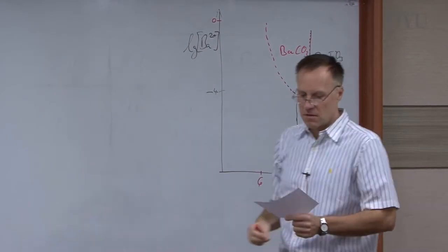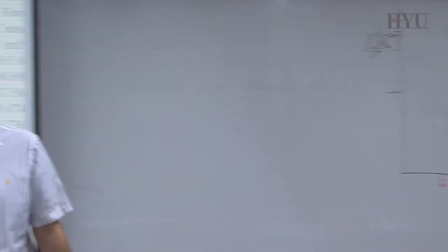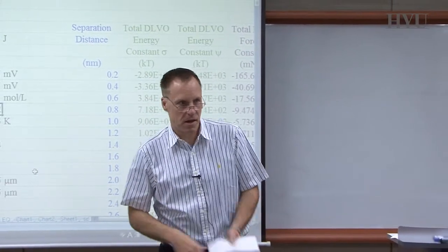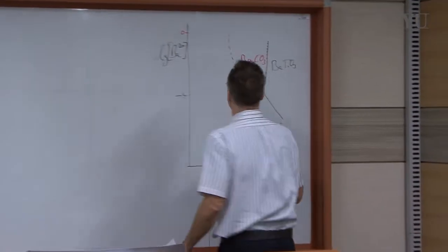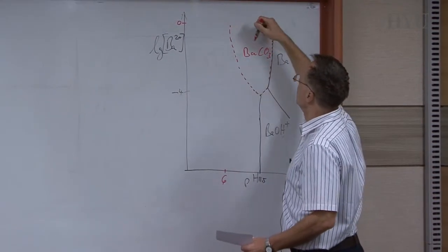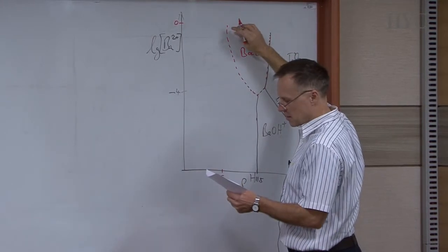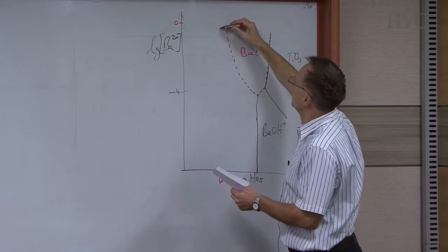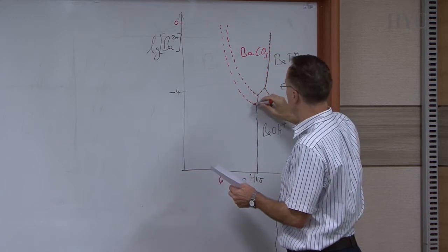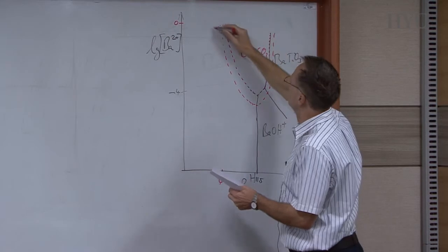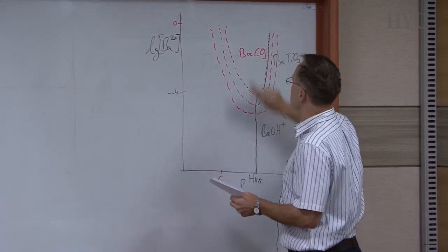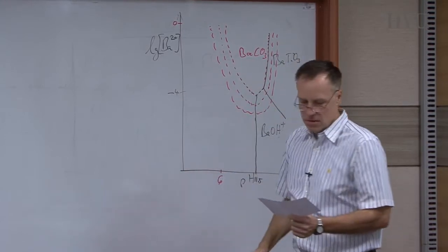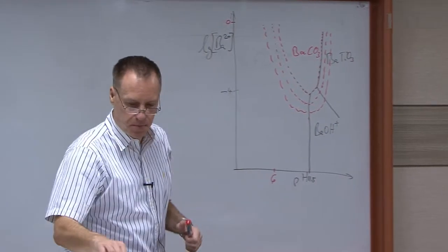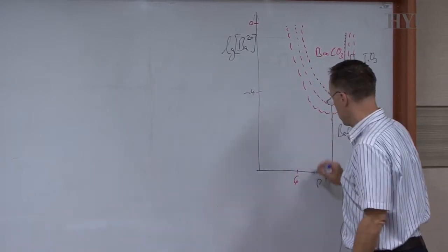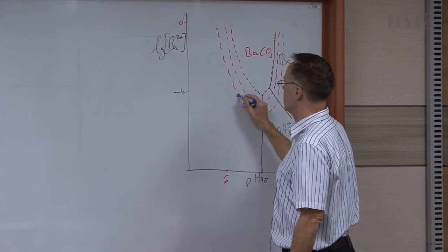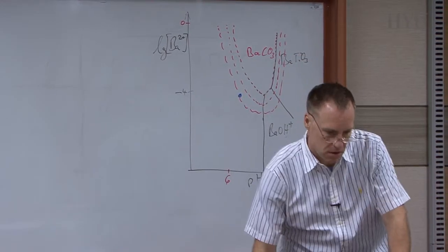And barium carbonate, of course, depends on how much carbon dioxide is in the system, because carbon dioxide is in equilibrium with carbonic acid in water. And when you put in more carbon dioxide, depending on the vapor pressure of carbon dioxide, you can actually increase the stability region. Yeah? So this is at normal levels from the atmosphere, but if you increase it, then you can move it to this region here. Yeah, so now you have a region where you can make a barium carbonate layer into the system, and let's pick a point here. So we see now around pH 8, we're in the range of 10 to -4. Yeah? So let's put this in.